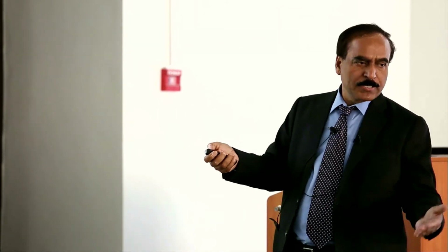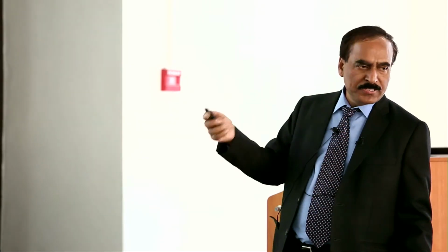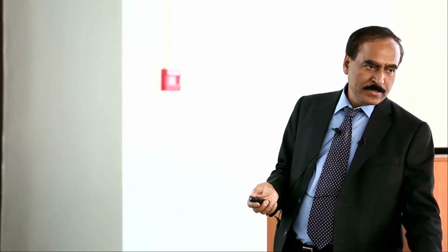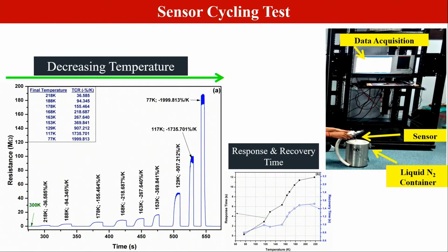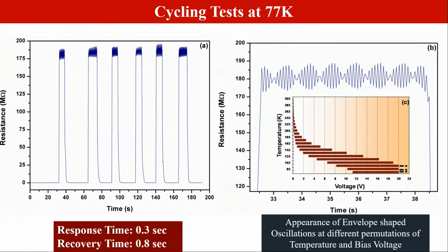It's so fast it will respond, because the TCR controls the sensing response time, also the recovery time, and the most important is the sensitivity and the resolution. All are linked with this 2000 TCR value. So, you can see here in the next slide, the response time is 0.3 second and recovery time is almost 0.8 seconds.